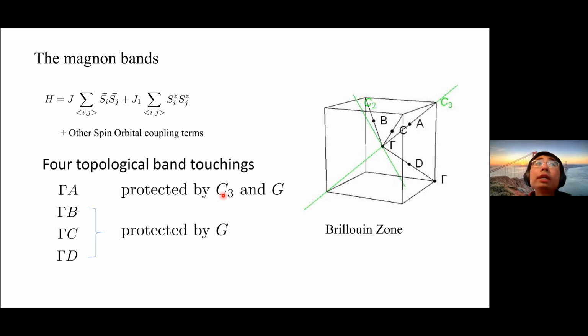Along the gamma A direction, there is a line node protected by 2 symmetries: one is a 3-fold rotational symmetry, the other is a glide reflection plane. The other nodes are 3 different axes along gamma B, gamma C, and gamma D. Actually, all of them lie within one of those glide planes, so these are protected by the glide symmetry.